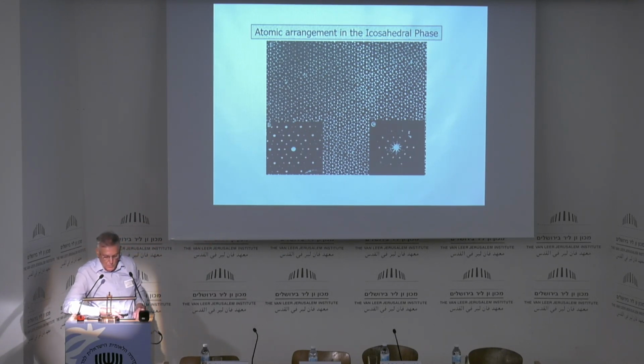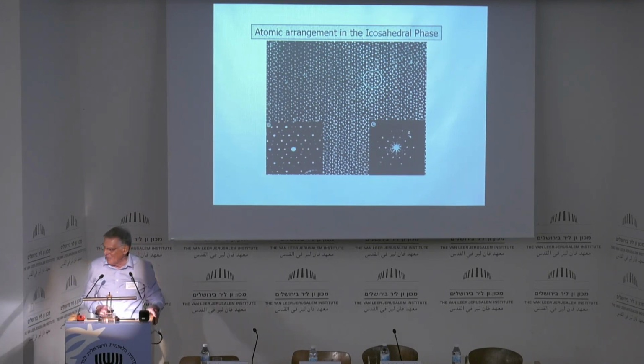But they did something more. They took an aperture here and shrunk it. And while it was shrinking, this pattern of the optical diffraction disappeared for lack of information, but it did not change on the way to disappearing. It did not change. No twins. This is a property of the structure on the atomic level.